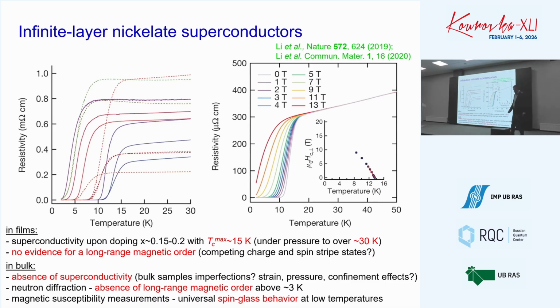And at the moment there is an unclear point about these materials, that superconductivity was found only in thin films. Of course, I can say that those thin films are somewhat strained, growing on top of strontium titanate. They experience some kind of pressure. You pressurize this square lattice of nickel ions somehow, and this acts as an external pressure.